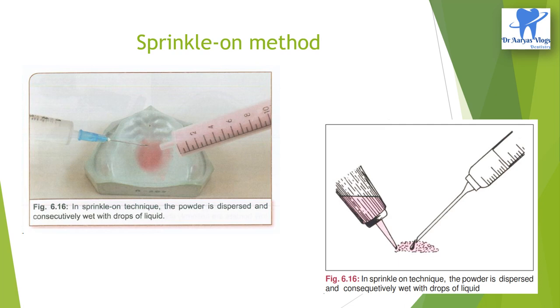What about the sprinkle-on technique? Here, the powder and liquid are loaded in separate dispensers. A small quantity of powder is sprinkled on a particular area over the cast and the liquid is sprinkled over the powder. So the powder is dispensed and consecutively wet with drops of liquid, which polymerizes the powder, and this continues till the entire ridge and associated landmarks are covered. The advantages are ease of use and minimal wastage of the material. That is about the sprinkle-on technique.